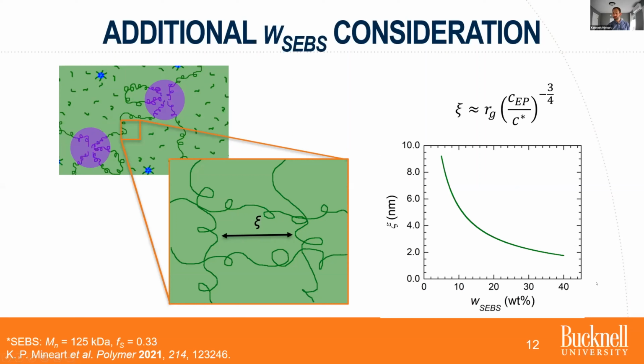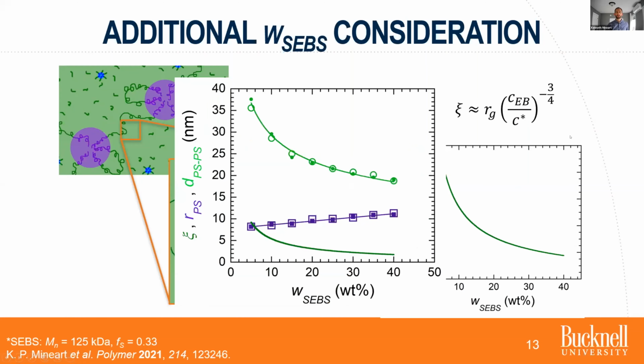And that calculation results in this trend here. Basically, again, as we increase the triblock copolymer concentration, the primary factor being changed here is this concentration in the numerator, and we see the mesh size decrease over that range. And so to summarize this overview of the structural behavior of these materials, it's important to realize that the mesh size is on a much smaller scale than the other dimensions that we were talking about, as shown by the dark green line at the bottom here. And so that'll come back into play when we start talking about transport properties.